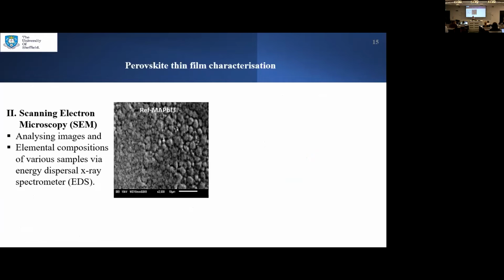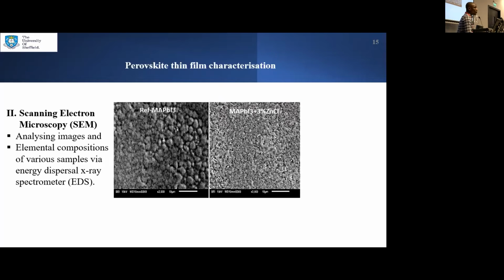Another way of determining the properties of perovskite is by using scanning electron microscopy. This is just an image of some of our results, where we used scanning electron microscopy to determine the surface morphology of our sample. Here is a reference sample of MAPI, that's methyl ammonium lead iodide. You can see they are well arranged with very large grains. But when we put in zinc chloride as an additive to see how it improved the surface, we realized that the surface tends to change. You can see the surface here changes, with very tiny grains.